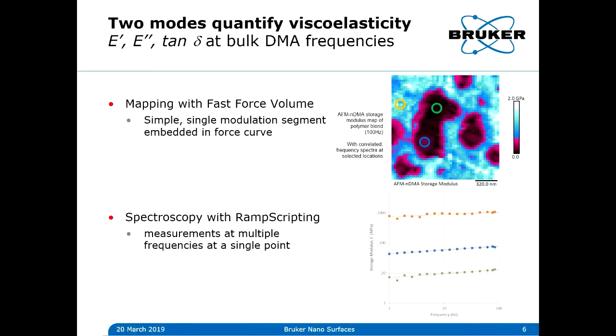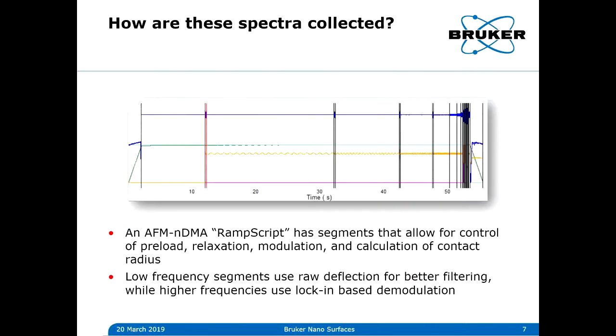So it takes about 15 minutes to collect a 48 by 48 point map like this at 100 hertz. But the individual spectra can take a bit longer, even up to several minutes at a single point. So a few tricks are needed to do this well. So here is some sample data.